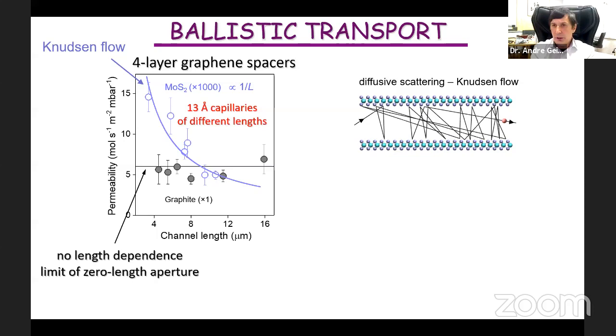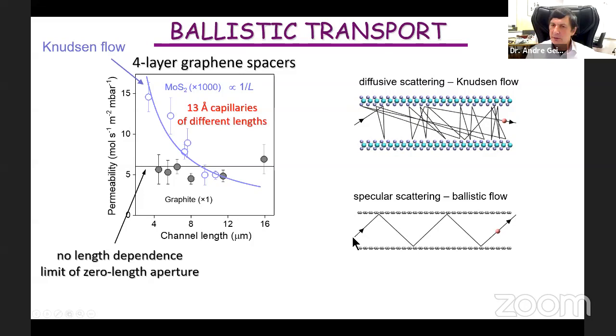Knudsen flow essentially assumes in its derivation that there is diffusive scattering: atoms entering the capillary go forward and backwards diffusively before eventually emerging at the other end of a long channel. If you have a very short channel, then everything which goes in goes out immediately. But another possibility is specular scattering. In this case, if an atom goes inside the channel, it goes deterministically to the other side of the channel. 100%, everything goes in, goes out, with a little bit of time delay, but it's like you get just an aperture, not a long channel. And this is what we believe is happening now: specular scattering in ballistic channels.